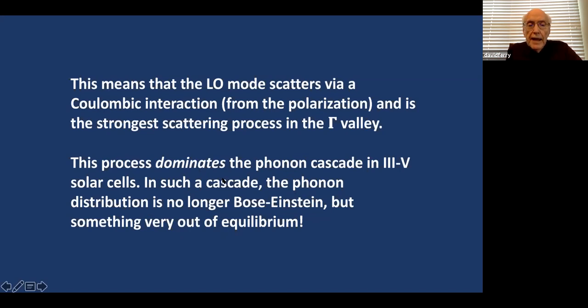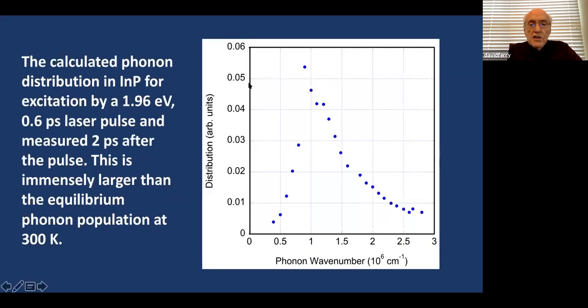Okay. Now we can look at that. This is indium phosphide. This is excited by a laser at 1.96 eV. It's a 0.6 picosecond pulse. And it's being measured 2 picoseconds after the pulse.